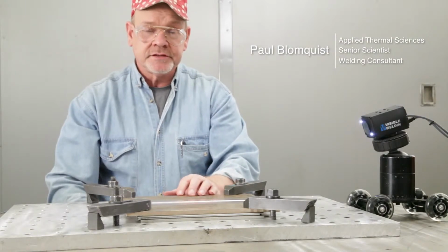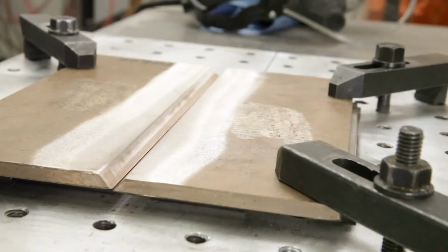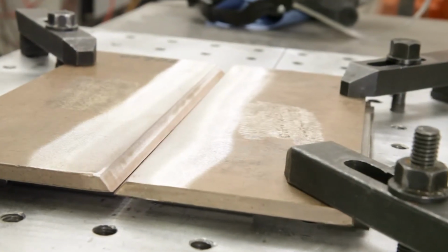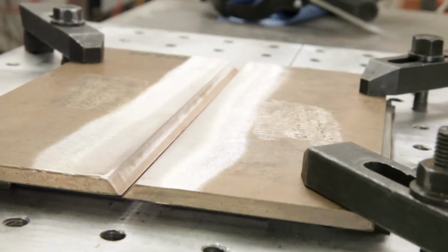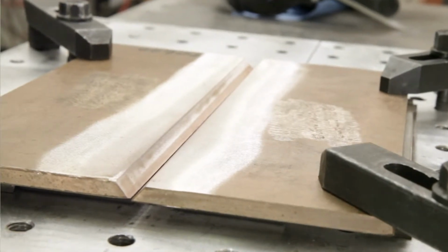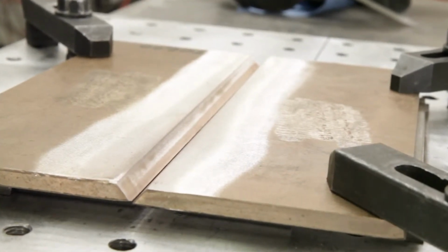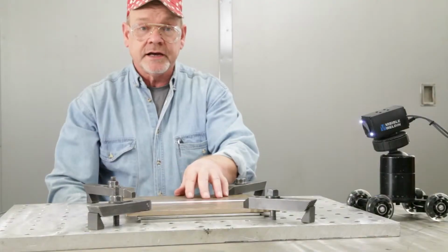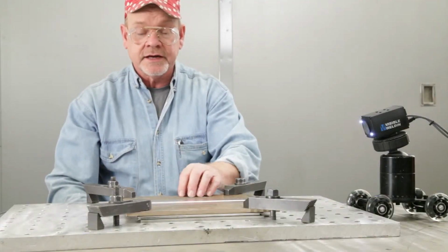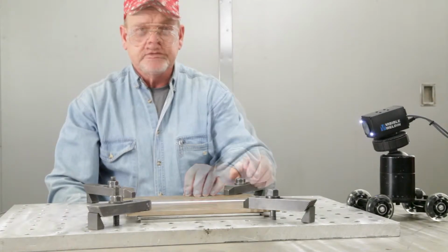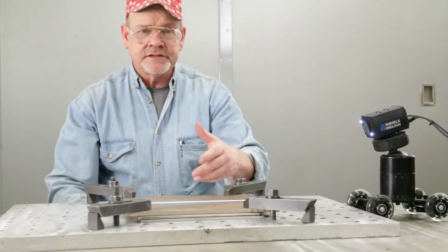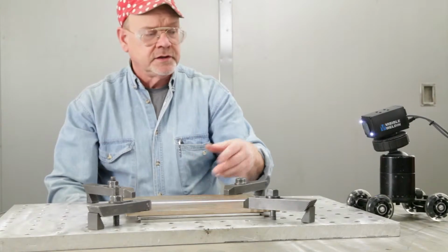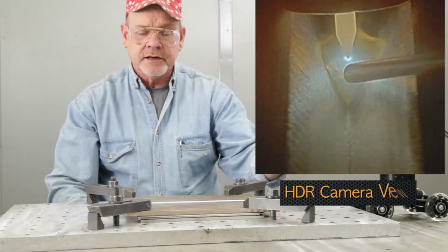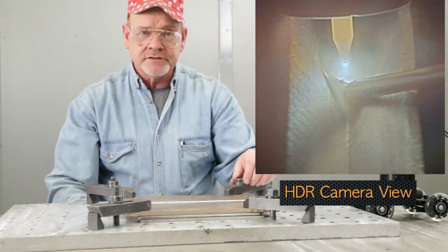We've prepared two pieces of 90-10 copper-nickel as we showed in the last segment. Notice that this is a tight root joint with a 70-degree included angle. We've spaced these plates above the fixture so there's no other material in contact with the back side of the joint. We will weld the first side and then turn it over, back grind the second side prior to second side welding. To give you a better picture of how the weld bead sets up and how the material flows, we'll be using a high dynamic range video camera to get close-up shots of the weld puddle.